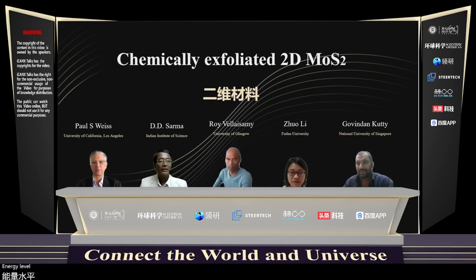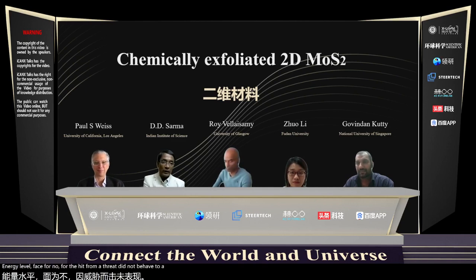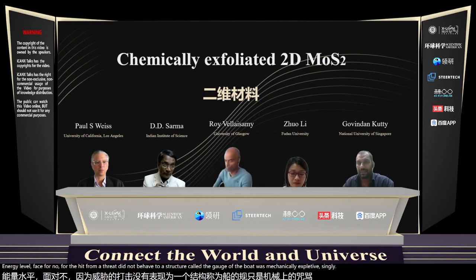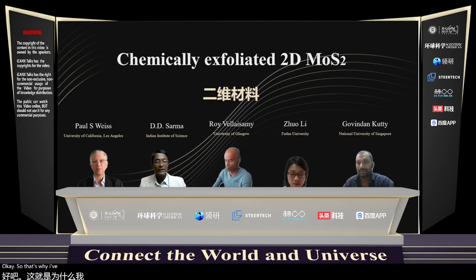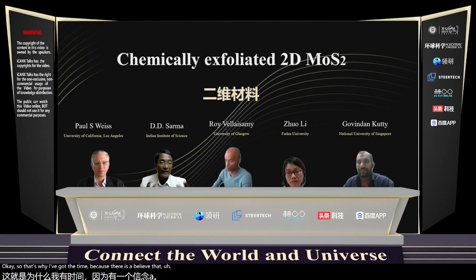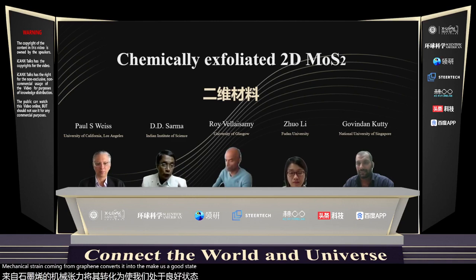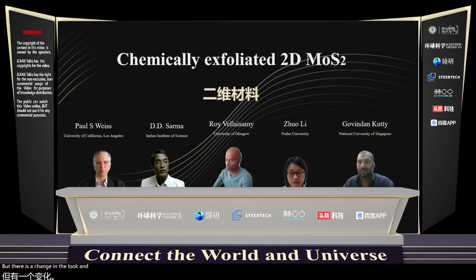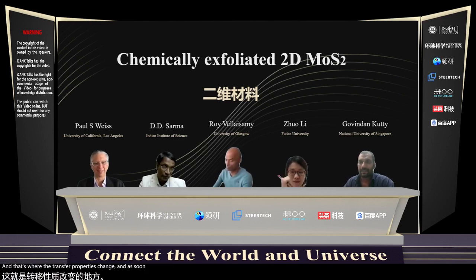The same claim applies for the doping studies and the shifting of energy levels. The heterostructure part that I talked about was mechanically exfoliated single layer of MoS2. I brought that in because there is a belief that the mechanical strain coming from graphene converts it into the metastable state. But what we show is that it does not convert to the metastable state. It remains in the H state, but there's a change in the local chemical potential under the graphene. That's why the transport properties change, and so the device property would be affected.